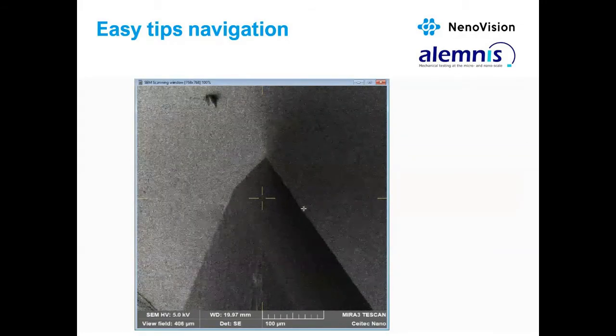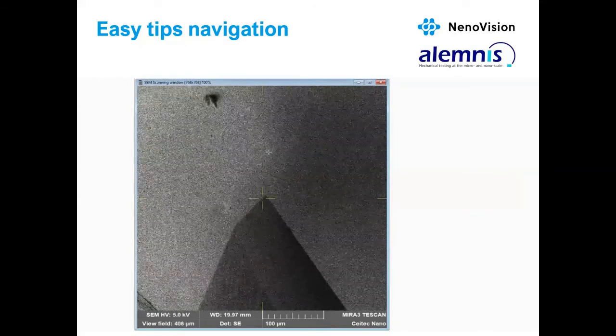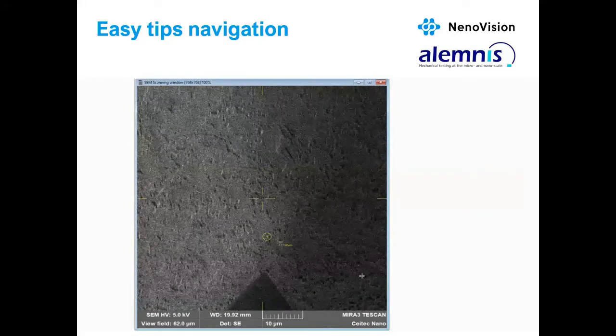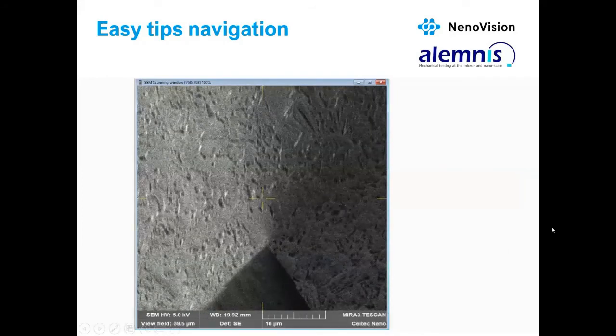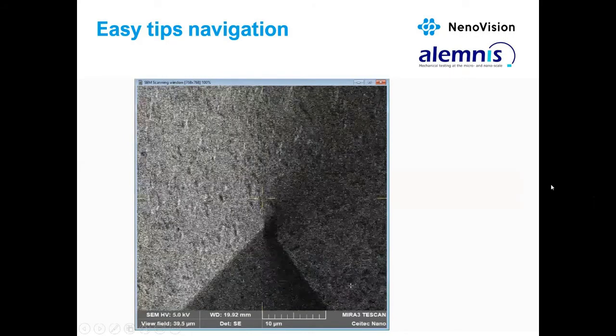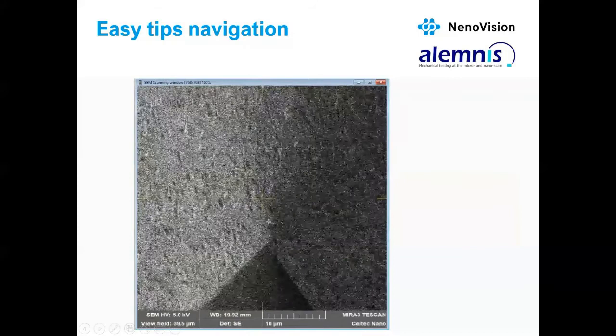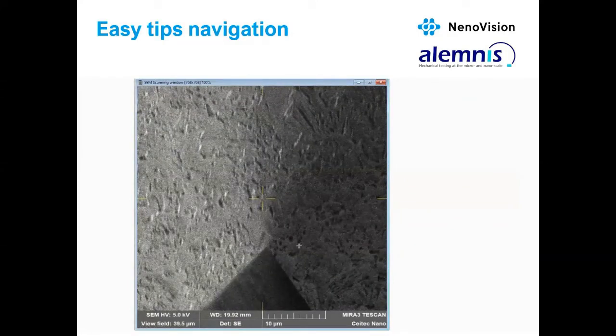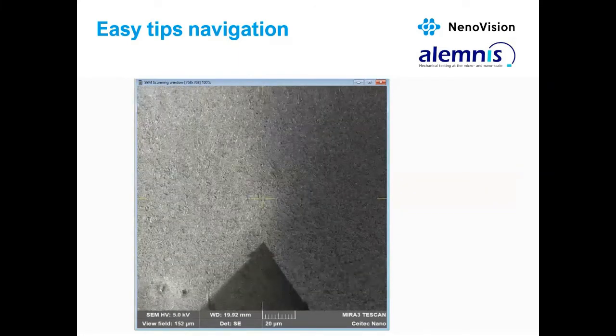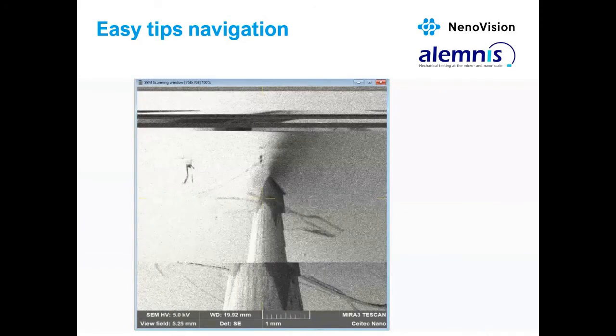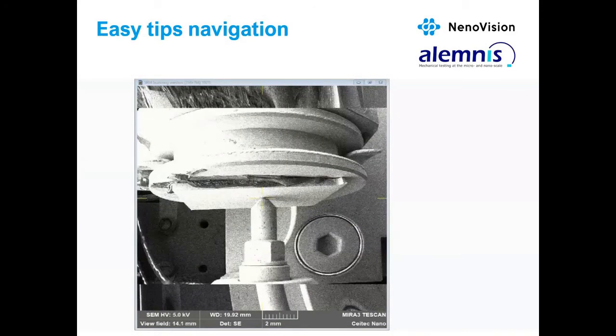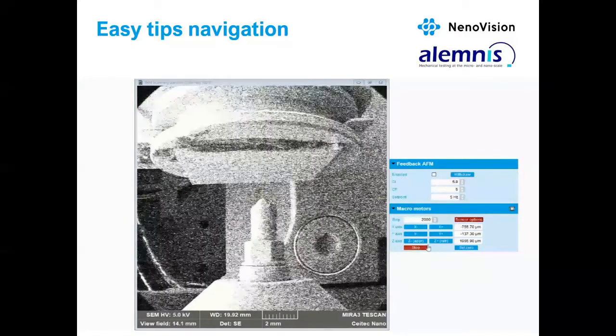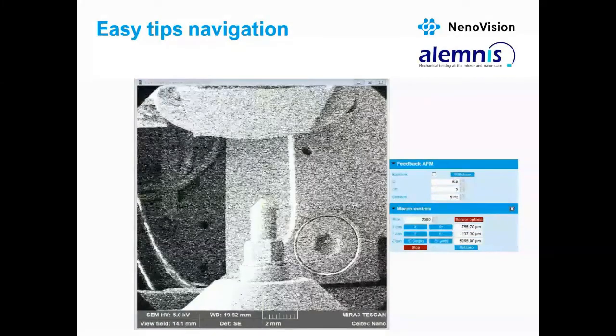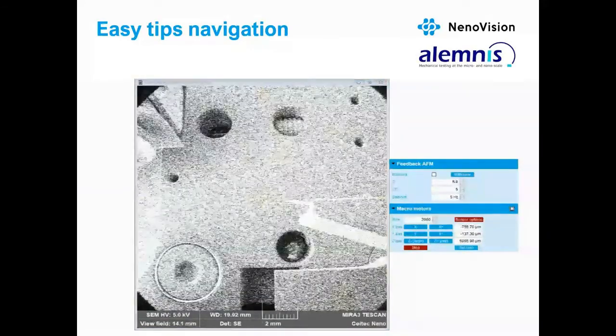From the shadow effect, you can see that we are getting very close to the sample. As you can see, this little circle here is the place where we would like to make the indent. The indent is done, and so we retract the sample and get away with the sample from the tip. As the SEM has the function for saving the positions, we save the positions of both tips.